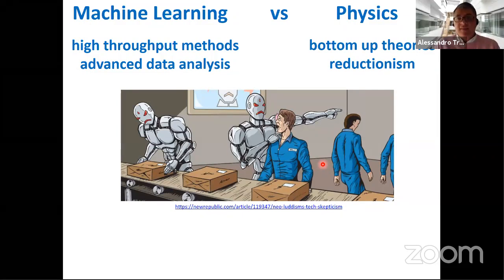Essentially, we've seen it already. It's a computational funnel problem, and the order in which you do it is that the largest narrowing of the funnel goes first. And so here the largest narrowing is from all structures to semiconductors. Then the second largest is from semiconductors to potential singlet fission. Then for the annihilation, of course, it becomes a problem-by-problem situation. So we end up with a data set which is 200. And so for those 200, we can look at the details.